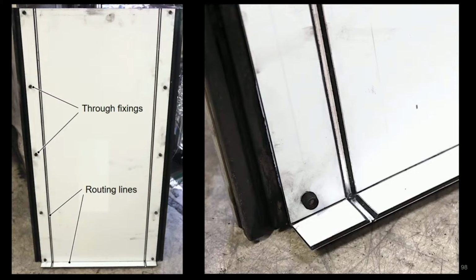And we've done this so as to fold it to create the horizontal ledge that you can see at its base. We've also routed vertical lines down the sides of the ACM panels so as to create free-floating, if you will, plates of aluminium which are attached to the sample only via the ACM's polyethylene core. Otherwise, the bolts that you can see down the side of the sample would have held that inside face in place. And this is akin to the condition that would exist on the inside face of an ACM rain screen cassette, which is obviously why we've done it, such as those used at Grenfell Tower.